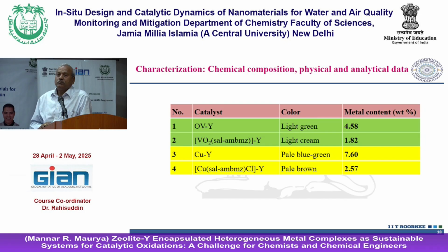one more. What is that? Metal content, other method for the metal content estimation. Okay, so we can see that once metal content is there, still we cannot say that this is encapsulated. Then you have to determine the nitrogen. Nitrogen, like any method, can be used. Most of the ligands have nitrogen content, and metal content. So once you have the metal and nitrogen content available, you can approximate the formula of the compound.